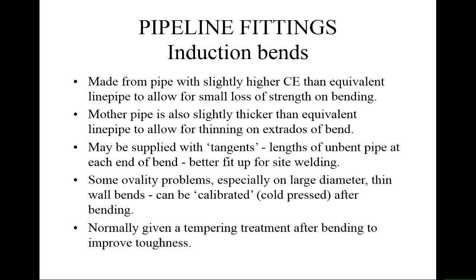And after bending, you have to look at the possibility of high cooling rates that have occurred because parts of the pipe are not heated. So there's quite a high thermal gradient from the heated areas to the unheated areas, and there's a possibility you could get martensite formation. So you temper them just to make sure that that isn't a problem.